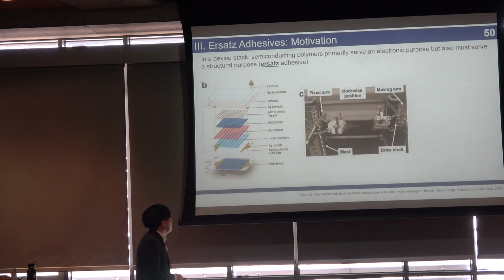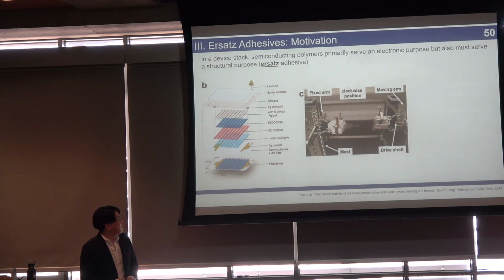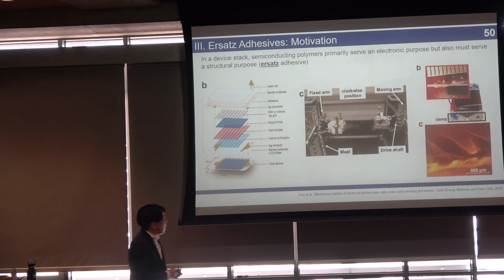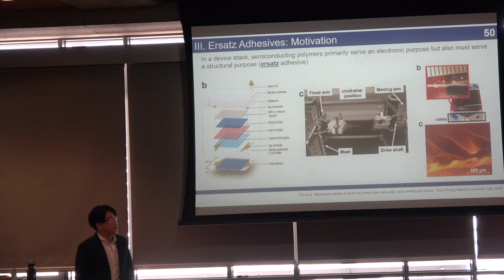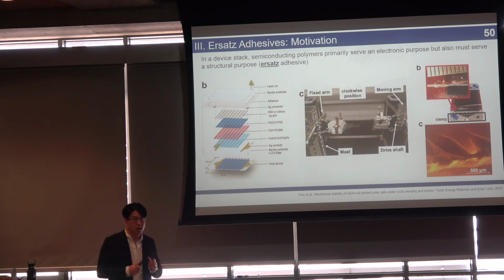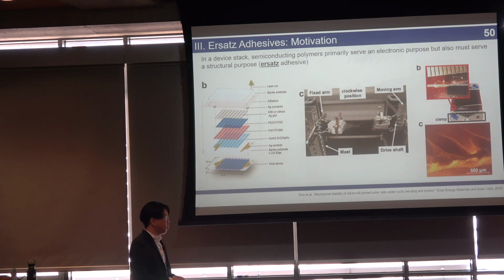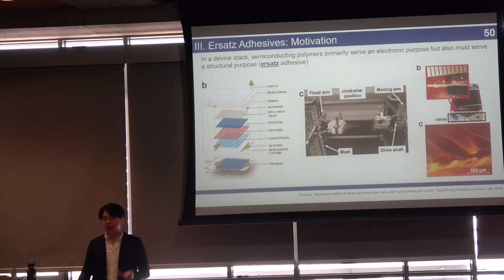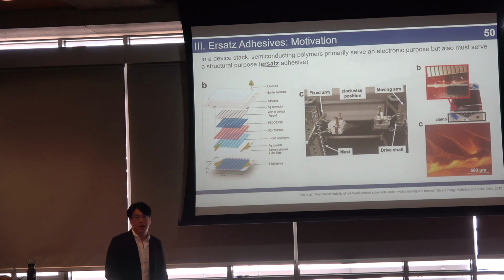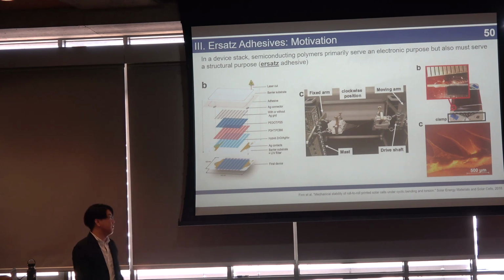And work by a previous graduate student, Dr. Mickey Finn, and her group built this torsional machine where he got this solar cell and he twisted it a bunch. And he found that, well, after thousands of cycles, you actually get delamination of these solar cells at the P3HT:PCBM and PEDOT:PSS interfaces. So we set out to have a deeper understanding of what's going on here and how we could potentially improve the adhesive function.